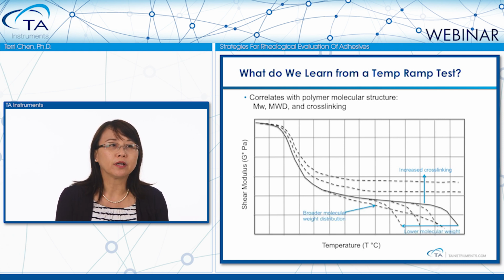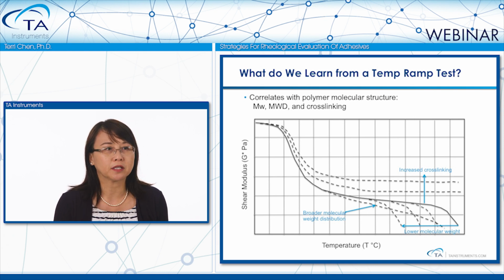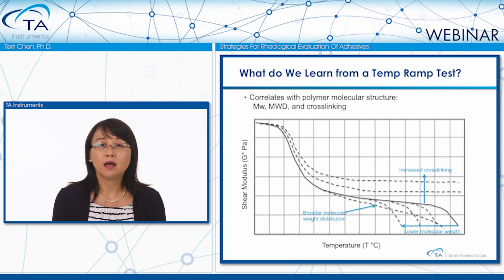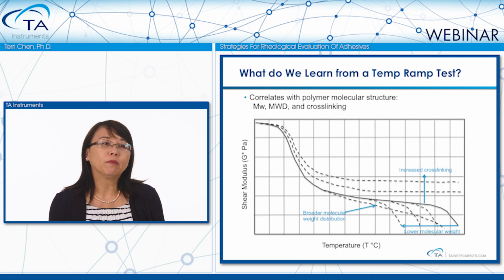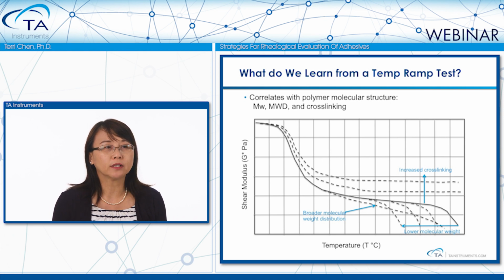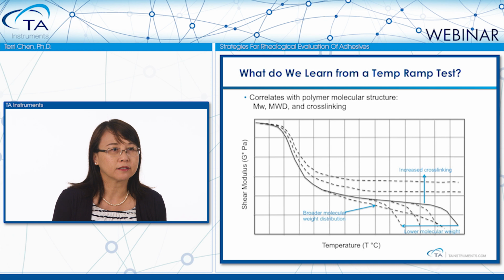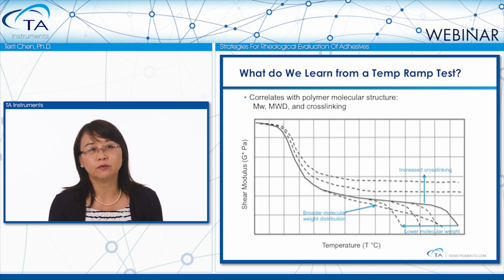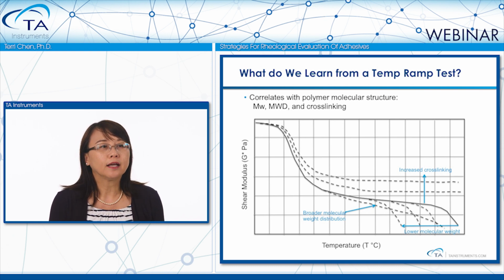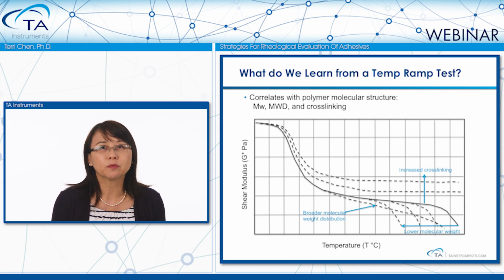Here is the summary of the polymer structural information we can obtain from a temperature ramp experiment. As we can see, when we perform a temperature ramp experiment from below glass transition up to the molten state, the modulus of the material changes over 5 to 7 decades. It goes from a glass-like solid all the way to a honey-like liquid. In this case, it is very challenging to use one single size geometry in one continuous procedure to obtain good temperature ramp results.